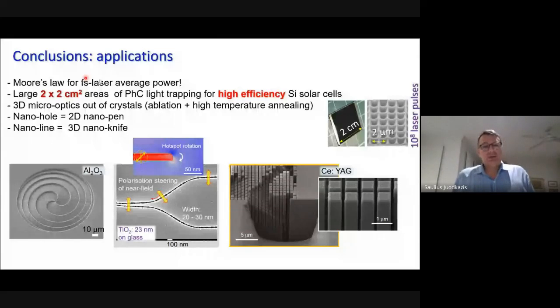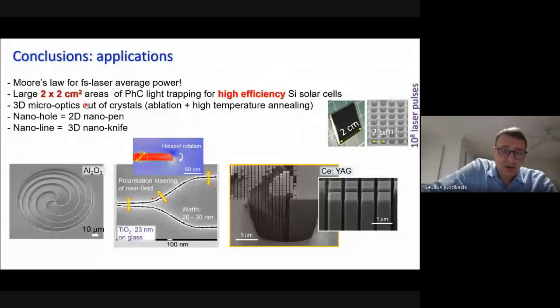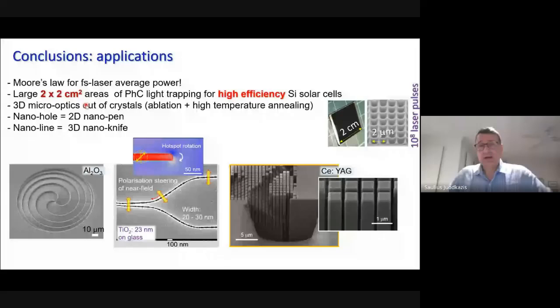Large areas, okay, large areas at the moment, only 2 by 2 centimeters for us for solar cells. But again, if you think about solar cell and patterning surface to get dense, no complex deposition and lithography, right? So it's really a practical and simple technique to fabricate large areas for efficient solar cell trapping and solar cells with the breaking ray optics, Lambertian limit. They can perform at the maximum efficiencies. And this is very important for thin solar cells.